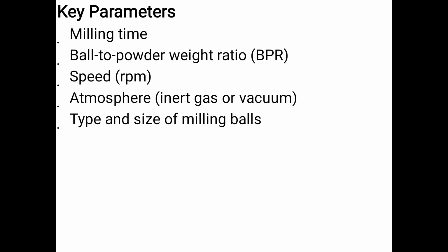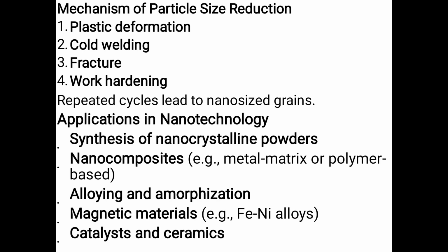Key parameters. Key parameters to be considered are the milling time, ball to powder weight ratio, the speed of milling, atmosphere in the form of inert gas or vacuum, and the type and size of the milling balls.